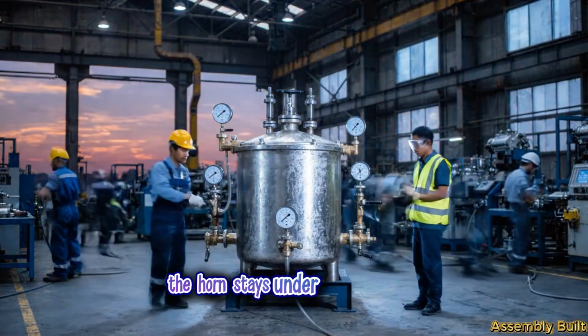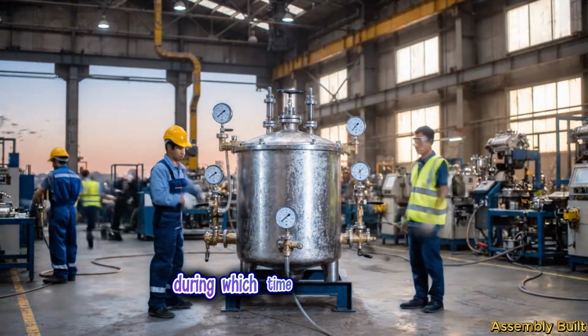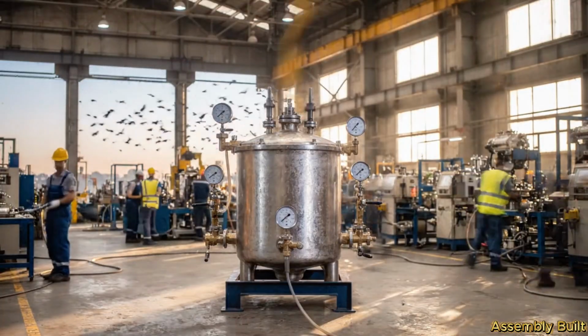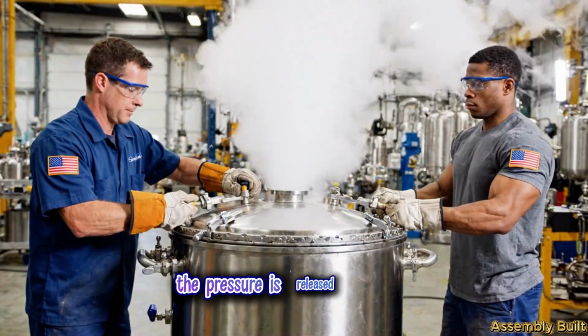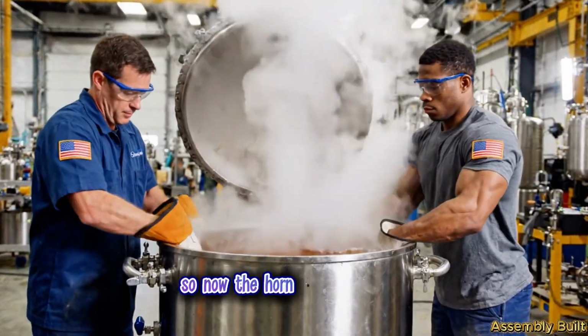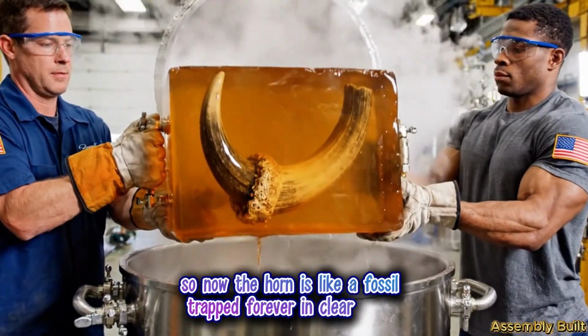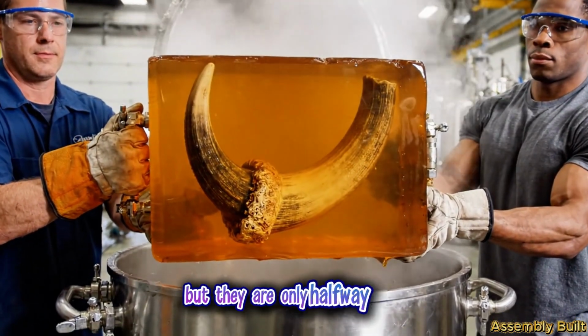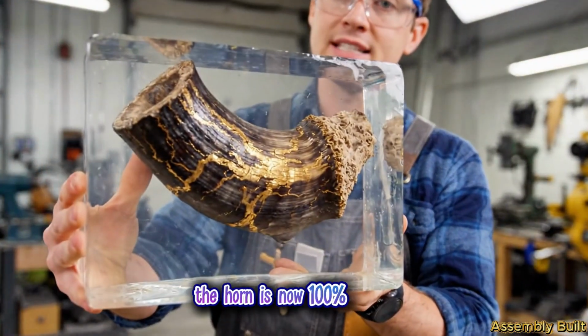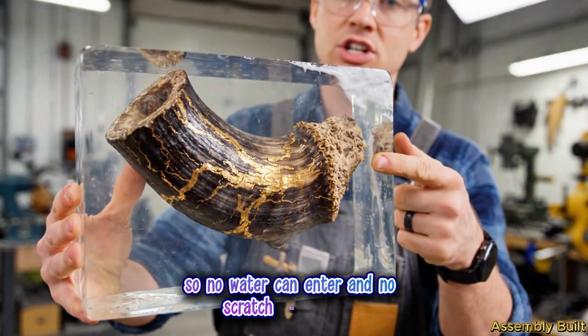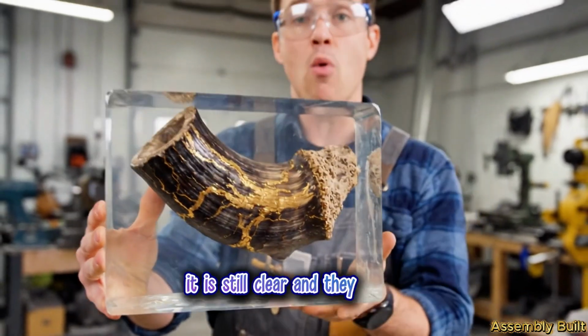The horn stays under pressure for 24 hours, during which time the resin cures and becomes solid. The pressure is released and the resin has cured, so now the horn is like a fossil trapped forever in clear amber. But they are only halfway done. The horn is now 100% sealed, so no water can enter and no scratch can reach it. It is still clear, and they want matte black.